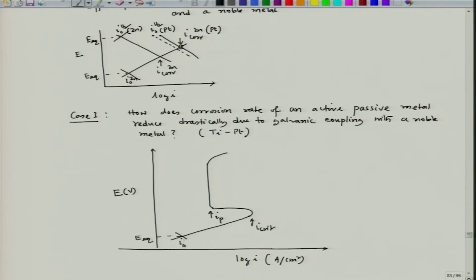This is I0 titanium on the titanium surface, and let us say this titanium is showing passivity in an acid medium, and the hydrogen evolution reaction becomes my cathodic reaction. So, on the titanium surface, if I plot it with a different color, it can have its own plot. This is basically E equilibrium hydrogen and I0 hydrogen over titanium surface. So, this is the typical plot, and the intersection point is at this point.